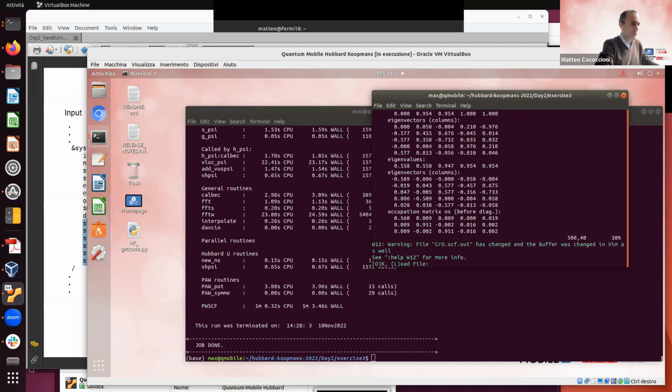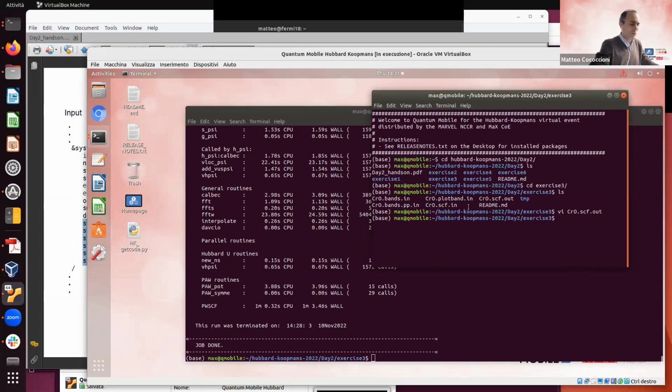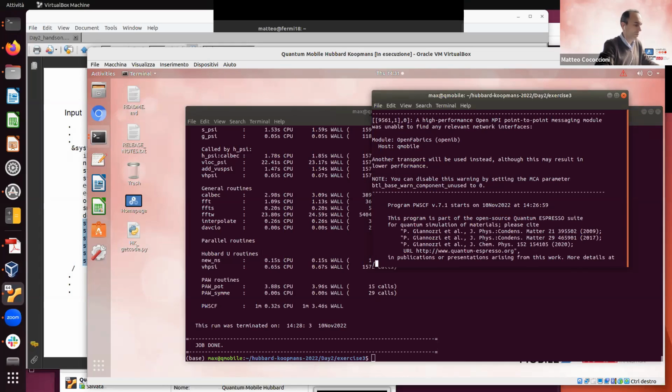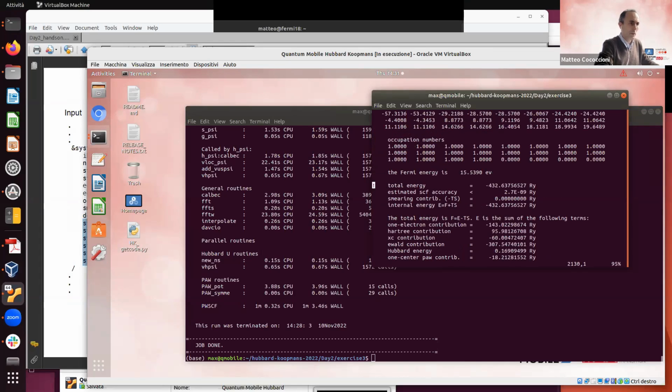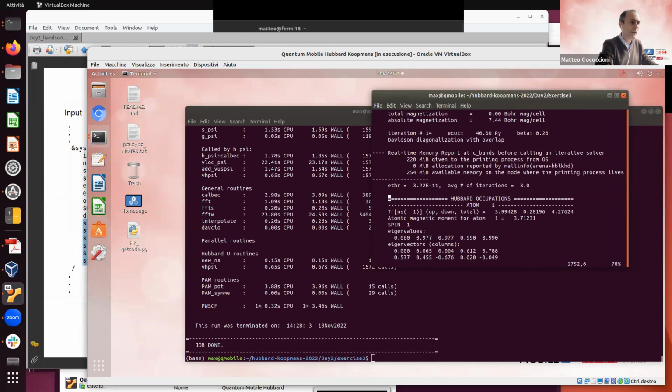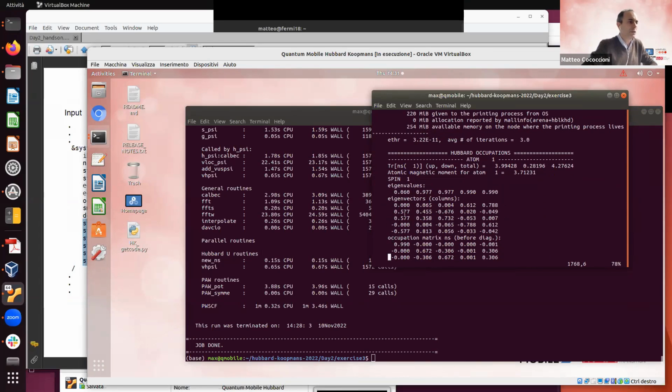So let's go. Now this has been modified since I opened it, and now we can take a look at what happened. So now we got an insulating ground state. And here it is. You see that the state we suggested to have zero occupation still has almost zero occupation. So the system liked this suggestion, got into this, at least local, minimum of the energy.